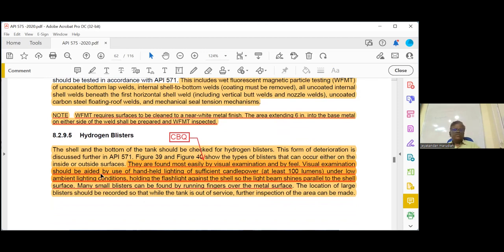Hydrogen blisters. Visual examination should be aided by use of handheld lighting of sufficient candle power, at least 100 lumens under low ambient lighting, holding the flashlight against the shell so the light beam shines parallel to the shell surface. Many small blisters can be found by running the fingers over the metal surface.